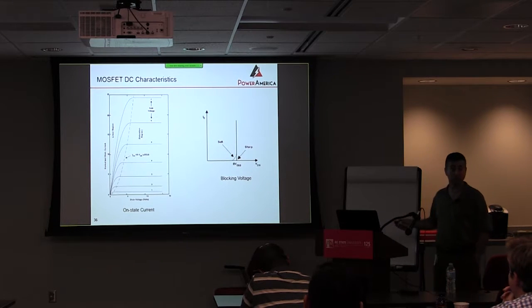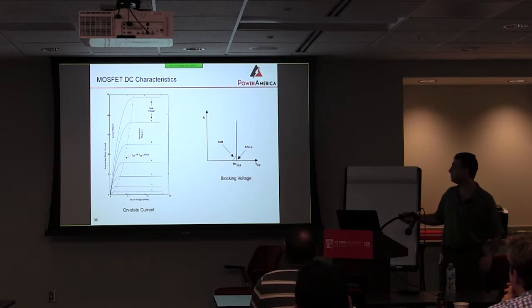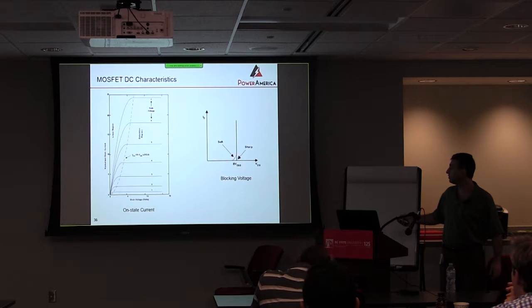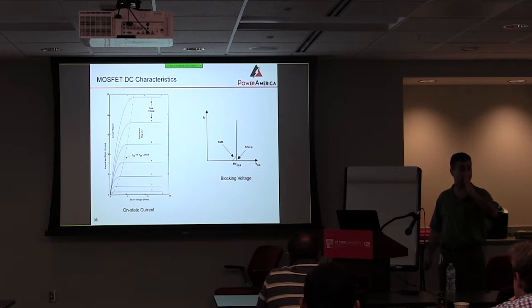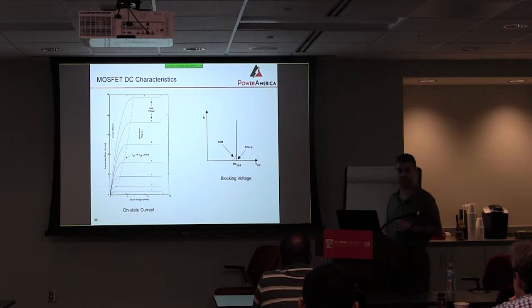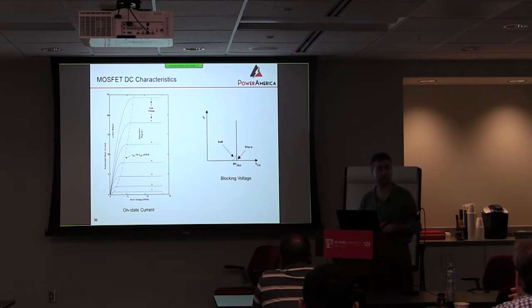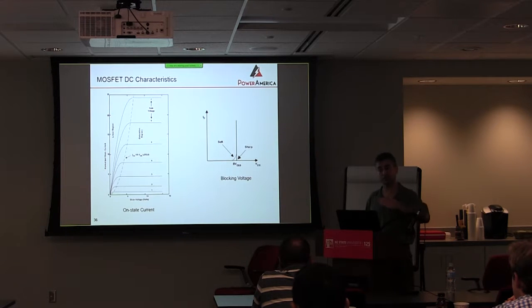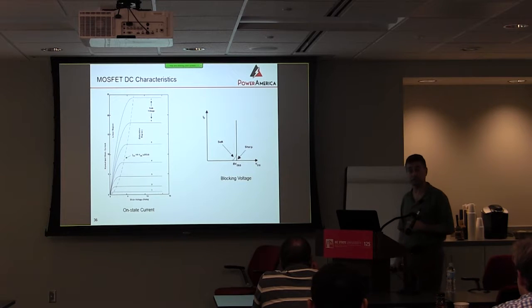One thing to make a note of is when you look at the blocking voltage of a device, you've got to look at this curve, the blocking curve, to see if you have a soft or a sharp knee, right? If you have a soft knee, like this one here, in a lot of cases it's an indication of some sort of processing or material defect. And typically devices that show a soft breakdown, in my experience, if you keep biasing them and stressing them, you get softer and softer, and at some point the device will basically fail.